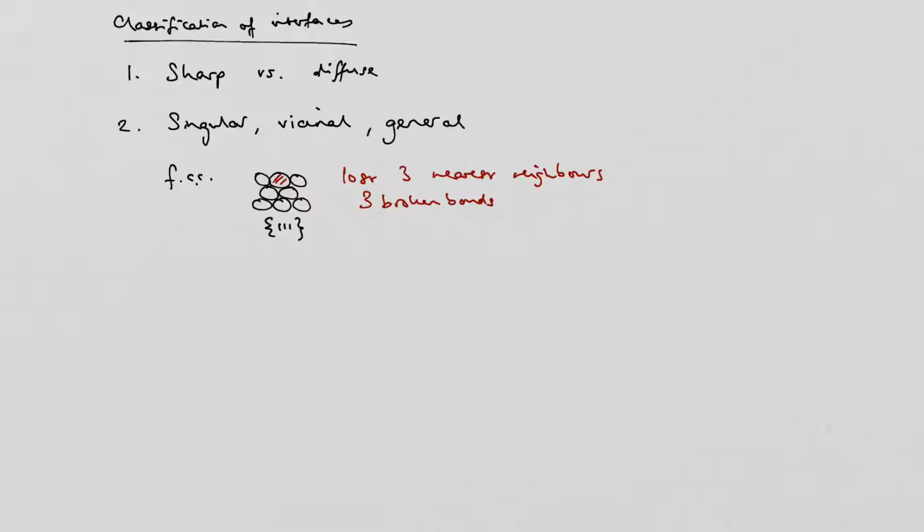And so that leads to an excess internal energy of 3/2 epsilon compared to the bulk. If each bond is worth epsilon in energy, then each atom actually is shared between. Each atom has other neighbours down, but typically a bond is shared between 2. That's the point here, right? So you've got 3/2 of epsilon compared with the bulk there.